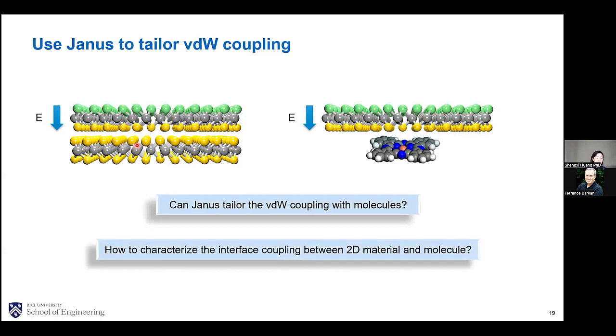How do we characterize the interface coupling between a 2D material and the molecule? Previously, we used low-frequency Raman modes, but now we can no longer use them, simply because those modes do not exist in the interface between a molecule and a 2D material. And this is because of the symmetry.